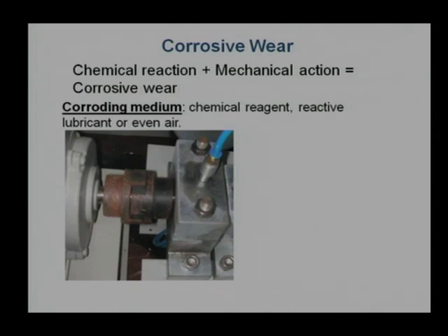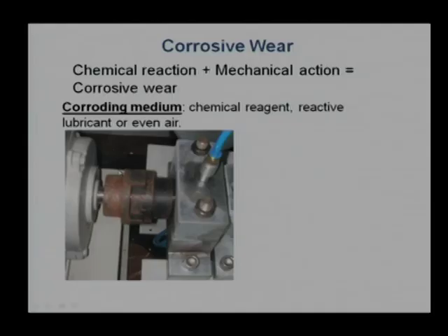And we know very well the couplings made of steel will be subjected to atmospheric reactions, and some sort of oxide layer will be formed on the surface. So there is a brown oxide layer on the surface. What we can figure out is that the dimension of this brown layer is slightly larger than the parent or initial dimension of the coupling. It swells, it increases in dimension, and this layer is also porous.